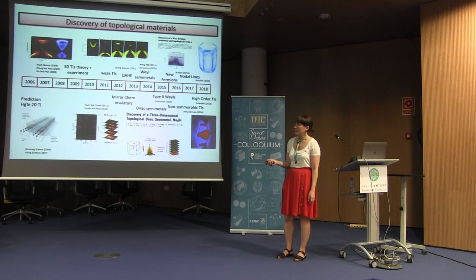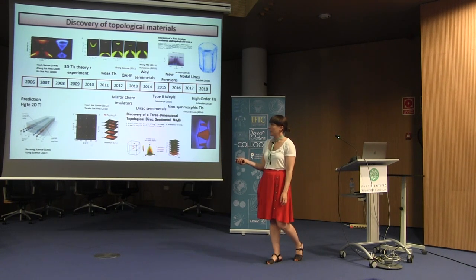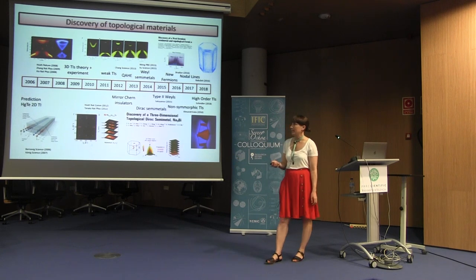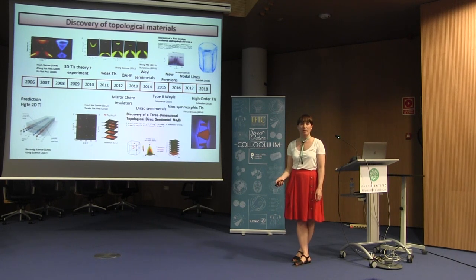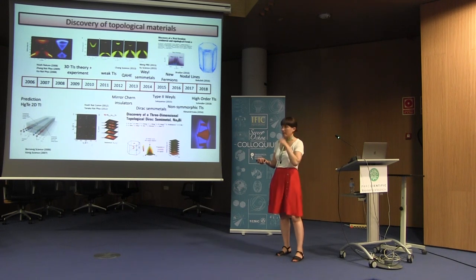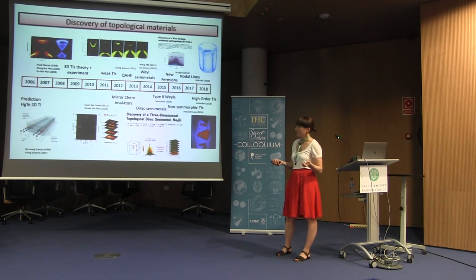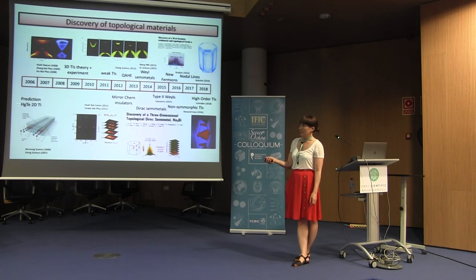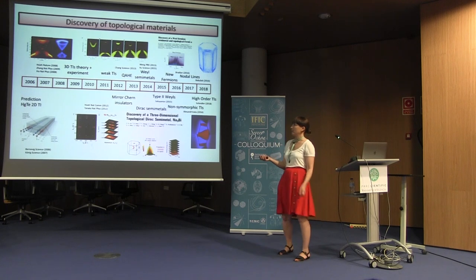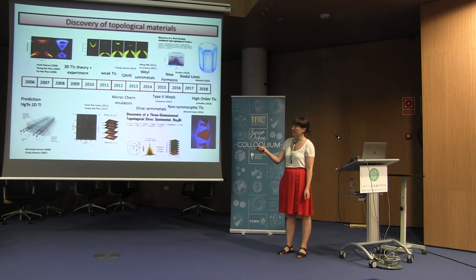The first prediction of a 2D topological insulator was done in 2006, and they predicted edge states in two-dimensional mercury telluride protected by time reversal symmetry. The experiment was done in 2007, and it was proved, it was actually measured, the Hall conductance. Later on, the 3D topological insulators, which is the version of 2D, were predicted, and also found experimentally with various techniques, where we could see the surface state. In the beginning, they were all protected by time reversal symmetry.